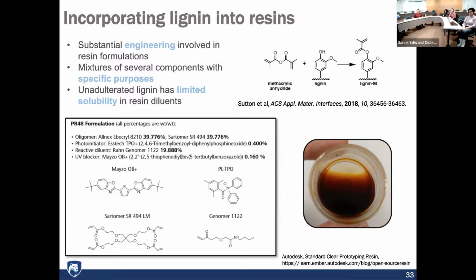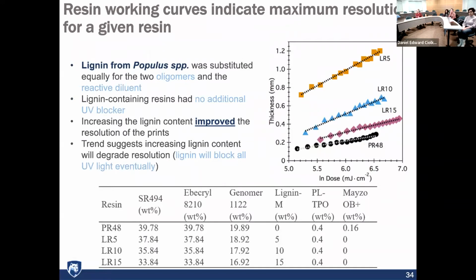So we started with this clear prototyping resin and added lignin to it. And what we can see, here's a plot of thickness versus the natural log of the dose. So how much light you add gives you how thick the material polymerizes, so how far the photons penetrate into the resin. And as you add lignin, what you see is that, so flatter is better. So even a large change in the amount of light gives you a small change in the thickness, which equates to really high resolution. Right, so you can make very small changes by adding more light, which is good for resolution. And what was sort of surprising was that our resolution actually got better as we added lignin.